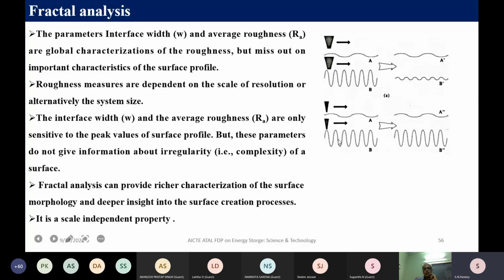Roughness measurements depend on the scale of resolution. With two different scales, we get different results. The interface width W and average roughness RA are only sensitive to the peak values of the surface profile.